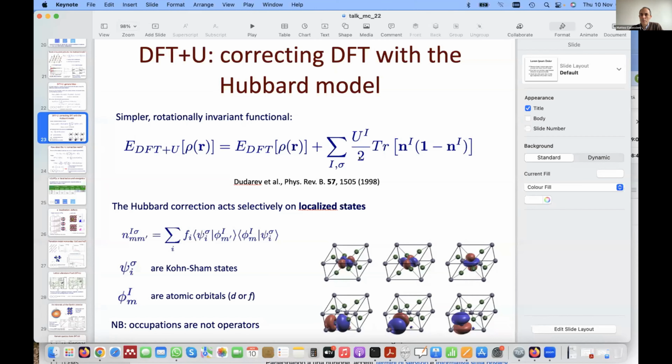When you work with an approximate functional, you miss that part, but you also misrepresent the first part. The Kohn-Sham gap is not what you would get with the exact functional. Now, the exact functional would have in its Kohn-Sham spectrum only the Kohn-Sham part of the band gap. So that would still not be the fundamental band gap, but from total energy calculation with a different number of electrons, you could recover the discontinuity of the potential and add it to the Kohn-Sham gap and get the exact fundamental band gap.